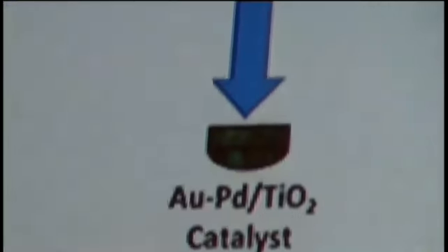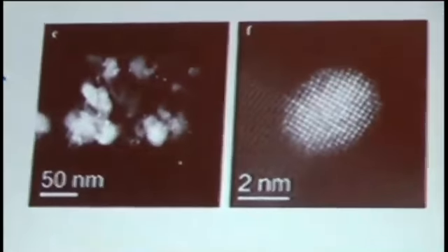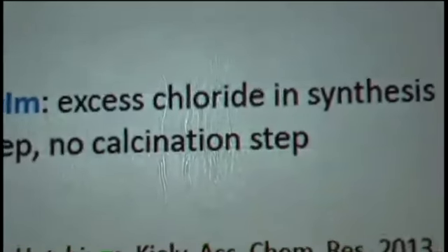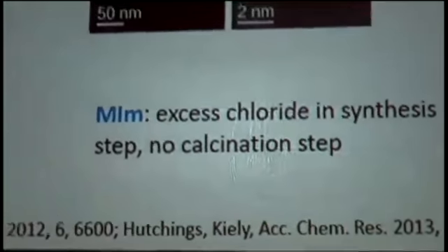The second important step of the modified impregnation method is that we omit the calcination step. So right after the wet impregnation and the drying, we go to a prolonged reduction period to get the final catalyst. This has been developed for gold palladium, and in our lab in Utrecht, Sankar then translated this method also for the synthesis of ruthenium palladium nanoalloys.